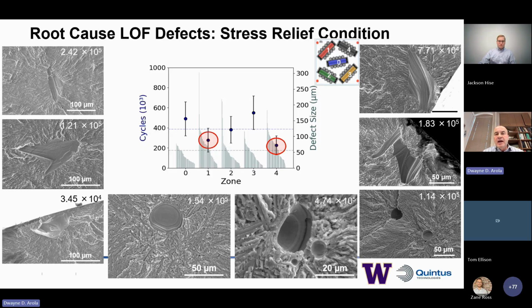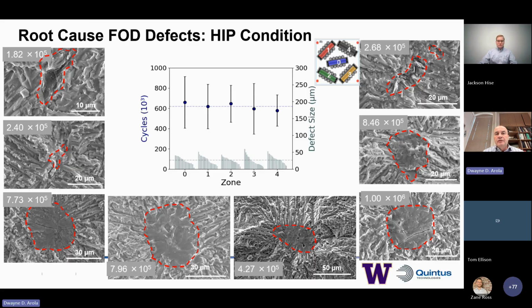If we do the same thing now for the HIP condition, we see, first of all, that the average life has increased substantially. As was alluded to before, this again is just distinguished in terms of an average. We also see that there's no distinct spatial difference across those 5 zones. So that treatment homogenized the metal.